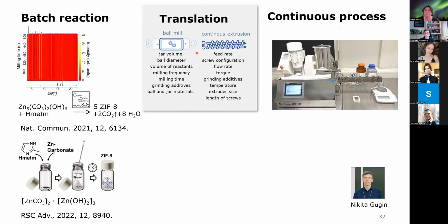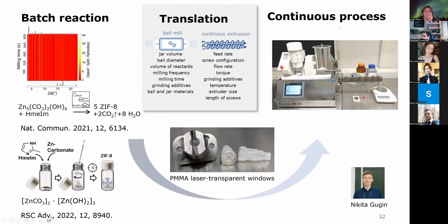And of course, our tool usually is to look into the processes. So we want to use in situ investigations again, and that would mean that somehow we need to look into this here. This is mostly steel or other materials, so there needs to be a solution, and you can see here the exchange for transparent windows at different positions, and then we're able to look into the reaction. So a bit of ex situ information up front. You can see here that you get an extrudate that can be washed, and then it already looks like ZIF-8. You can sometimes see also side phases appearing, but nevertheless, this works quite nicely.